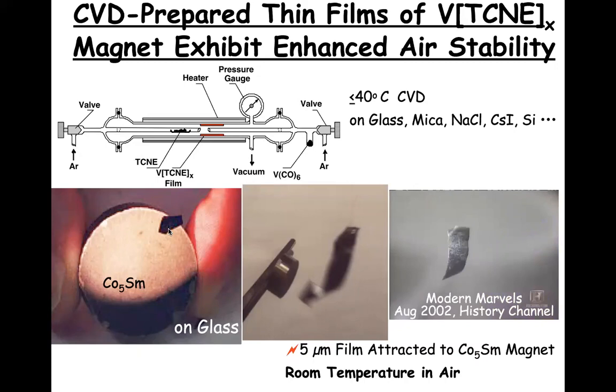And here's a piece of broken glass that's 99% by mass glass and less than 1% vanadium magnet, and it sticks to this cobalt samarium magnet. Here we've covered Teflon with the vanadium TCNE magnet, and you can see we caught a photograph of it flying through the air. It's being attracted to the cobalt samarium magnet. And here's a piece of iron aluminum that's coated with the vanadium magnet being attracted to this magnet over here. So it is a room temperature organic-based magnet that you can put on lots of materials.